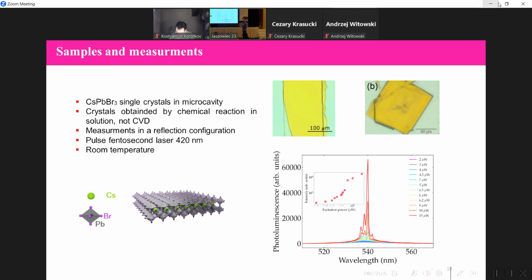But these crystals were not obtained by CVD, like in most works about this material, but just by chemical reaction in a solution. We carried out measurements in reflection configuration with a pulsed femtosecond laser at 420 nanometers, of course at room temperature.